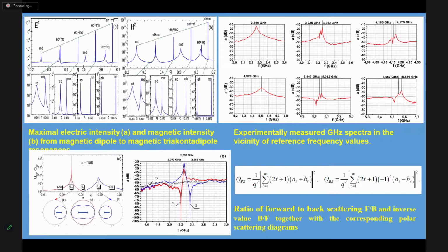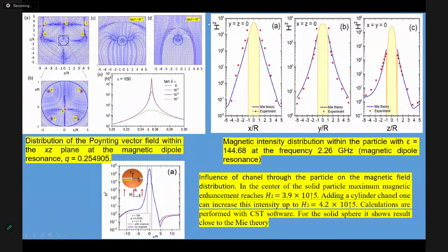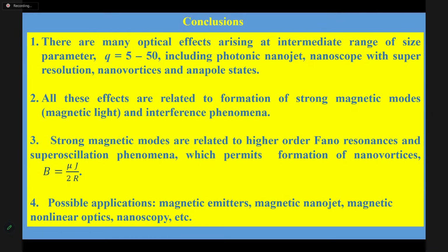They used for this purpose ceramics in the microwave range, with permittivity on the level of 150, to see how the electrical and magnetic field grows from one resonance to another. This experimental measurement showed that even for the first resonances, even for dipole resonances, it is possible to obtain a magnetic field enhancement of 1 million times, for example. So if you use high intensity, then it is possible to create magnetic fields comparable with fields in neutron stars.